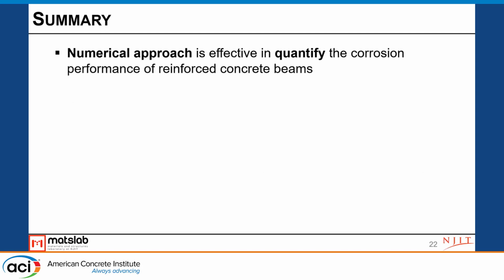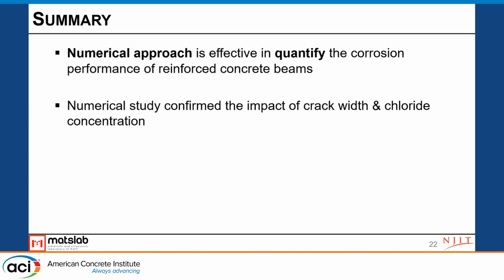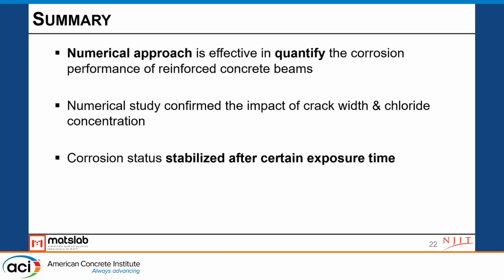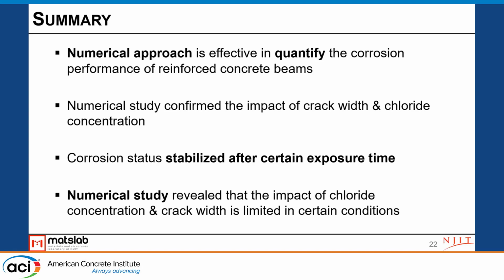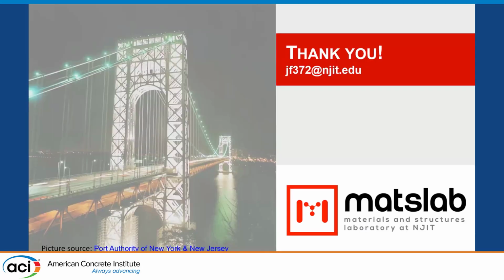So, here's the summary. From this numerical approach, we can say it is very effective in quantifying the corrosion performance. Through this numerical simulation, it confirmed the impact of crack width and surface chloride concentration, and that the corrosion started to stabilize at a certain time. However, the impact from surface chloride concentration and crack width is counterintuitive to what we think, and is actually limited in certain conditions. And yeah, that's it. Feel free to ask if you have any questions.